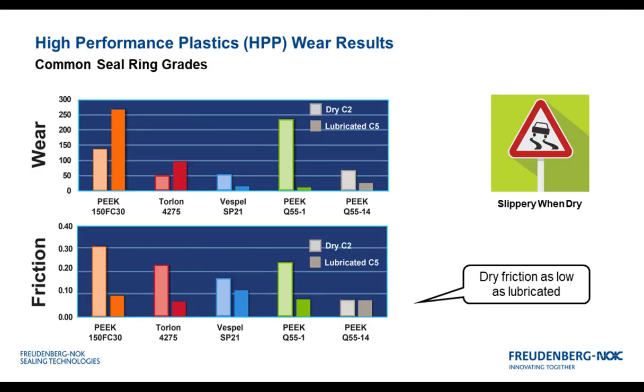FC30 is a material that's been around a long time. It's a very good material overall. The issue, I would say, is it's not been designed for dry running conditions. So when I call up that data in this graph, you can see the FC30 there. From a fatigue standpoint, it's actually pretty beneficial. If I'm concentrating on a fatigue failure, then I would make sure the filled system has the proper materials for it. So for example, the green material there is not a fatigue resistant material. It's not been designed for that. Its failure would be quicker than the FC30. But when you compare that to the 5514, that example is a material that's much more fatigue tolerant. Those are different failure modes that are tested for in different ways, so not shown in a wear and friction test here.